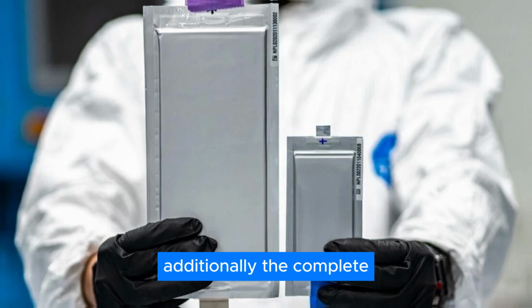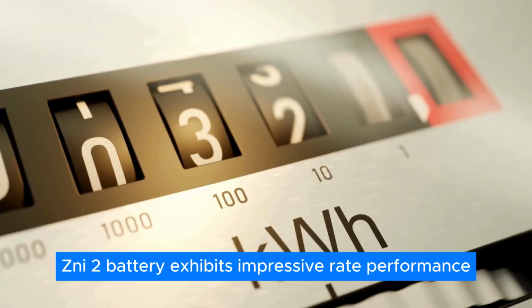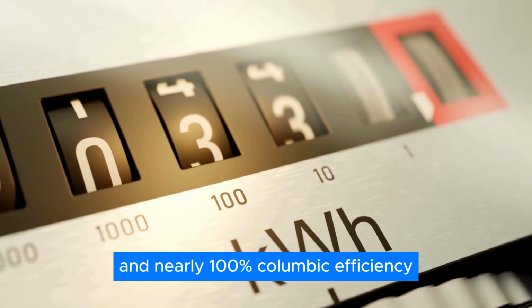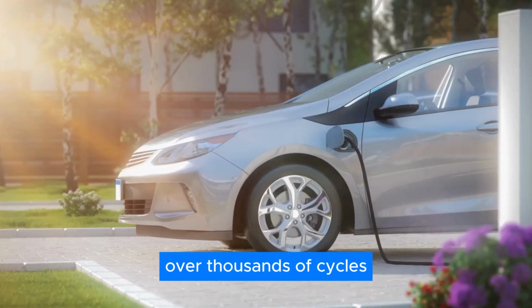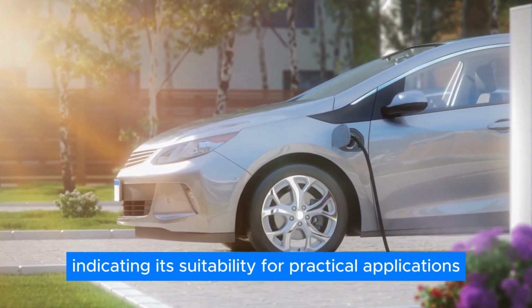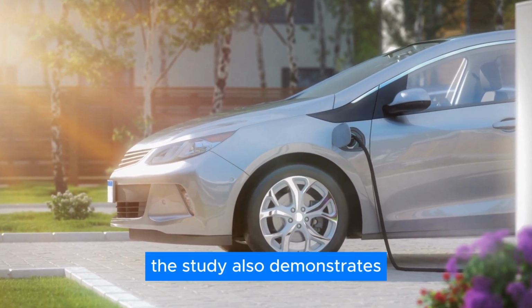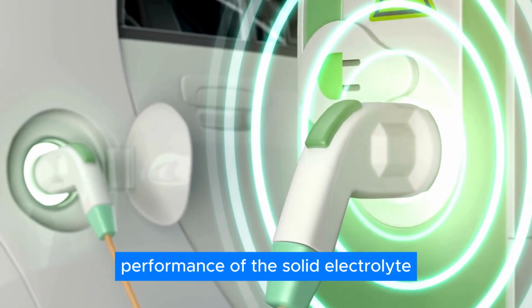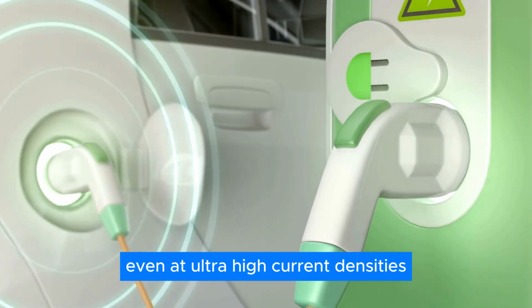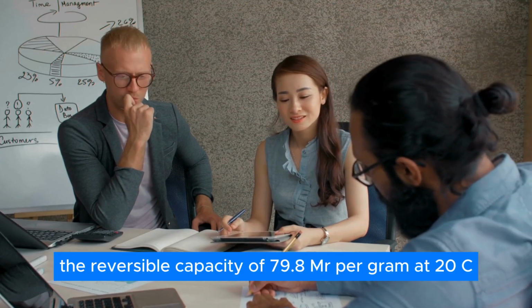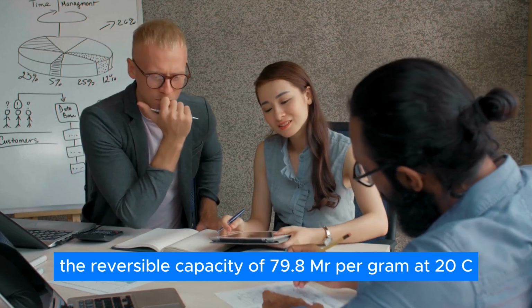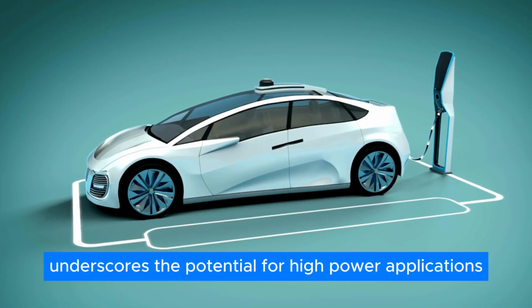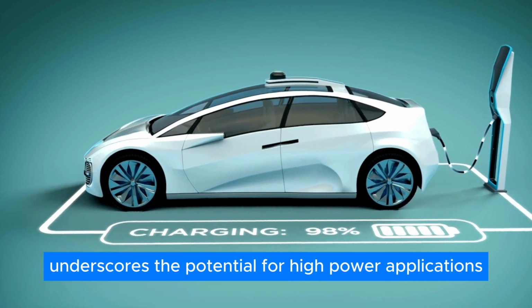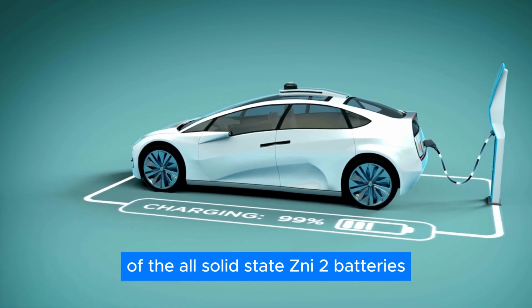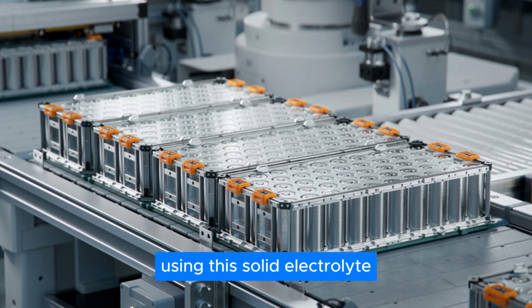Additionally, the complete ZnI2 battery exhibits impressive rate performance and nearly 100% coulombic efficiency over thousands of cycles, indicating its suitability for practical applications. The study also demonstrates the excellent rate performance of the solid electrolyte, even at ultra-high current densities. The reversible capacity of 79.8 mAh per gram at 20C current density underscores the potential for high-power applications of the all-solid-state ZnI2 batteries using this solid electrolyte.